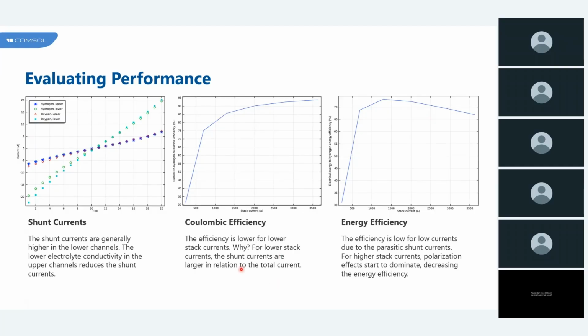If we are talking about the Coulombic efficiency, this is lower at the low stack currents, where the shunt current losses form a larger percentage of the total current. As we increase the stack current, Coulombic efficiency rises sharply, meaning more current goes toward the actual hydrogen production. Then we switch to the energy efficiency. It starts low due to early shunt current, and the polarization losses, peaks around 1300 amperes, where the system is operating optimally, and then drops again at high currents due to the ohmic and the activation losses. So this performance curve gives us a clear optimal operating window, where efficiency, reliability, and the cost are balanced.